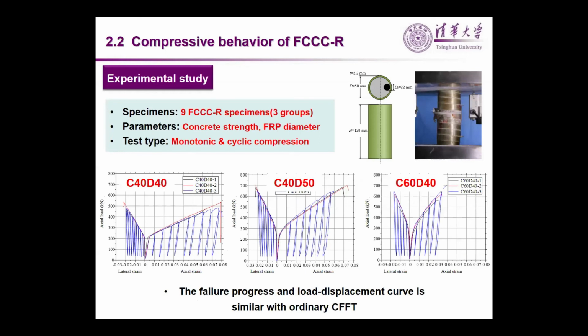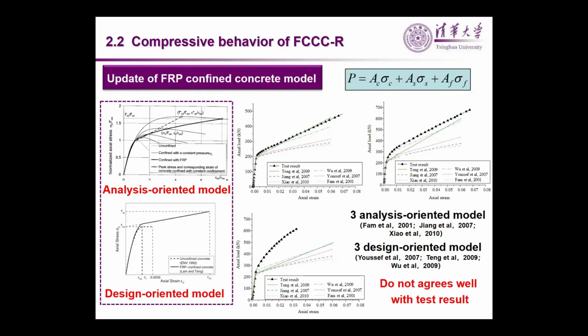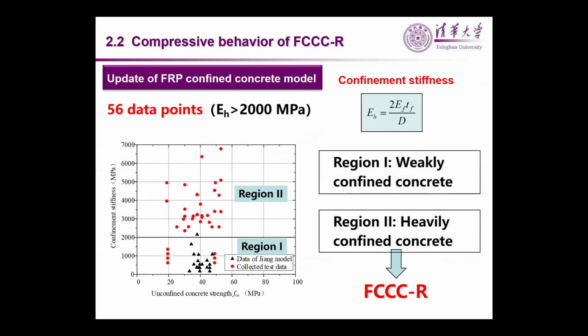six confined concrete models were chosen to calculate the load displacement curve. However, traditional theory of the FRP confined concrete illustrates obvious deviation in predicting axial compressive behavior of FCCR. And we believe that the reason for this phenomenon is that the thickness to diameter ratio of the FRP tube in FCCR is much larger compared with the ordinary CFFT, resulting in a much higher confinement stiffness. And it can be seen that most of the data used to calibrate the concrete models have a confinement stiffness less than 2000 megapascal, while that of the FCCR reaches around 3000 to 4000 megapascal.